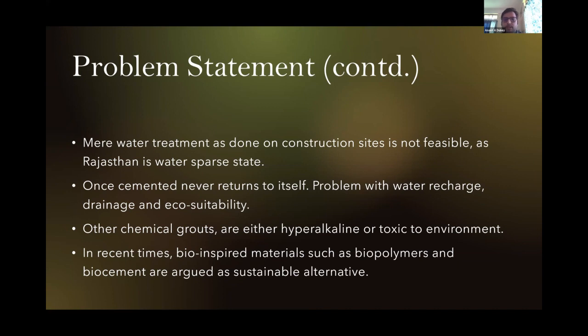There are several solutions which are in practice for desert erosion mitigation. The most common is water spraying, easy, accessible. The problem is that in desert areas, water is in very limited amount. So spraying is not that feasible. Moreover, once you spray the water, after drying, the sand or soil comes to the regular state and it is erodible again. And we have also shown this in our experiment.